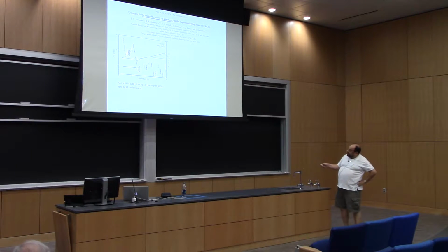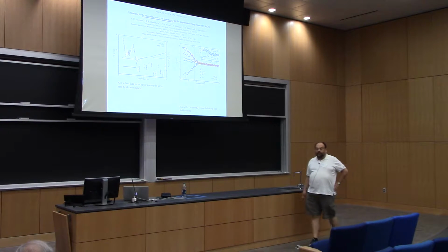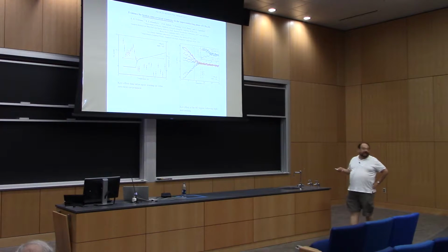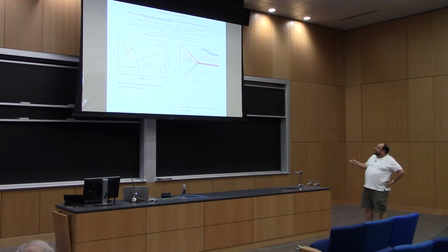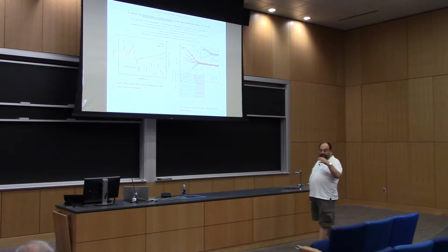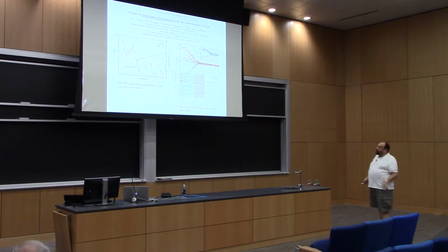This is the recent work from Kapitulnik's group, the Stanford work, where they claim that in the superconducting state, time reversal is broken. I think it's a very important paper. And they also say that in the hidden order state, time reversal is not broken. However, with application of a magnetic field, the system can be trained. So if it's field cooled at high field, then they see a Kerr effect. And heating it up can erase that Kerr effect. However, interestingly, the temperature at which it's erased is above the hidden order temperature. So you need to go beyond. That clearly suggests that there is some metastable physics beyond the mean field physics that can be induced by field cooling. I don't need to show this transparency again.